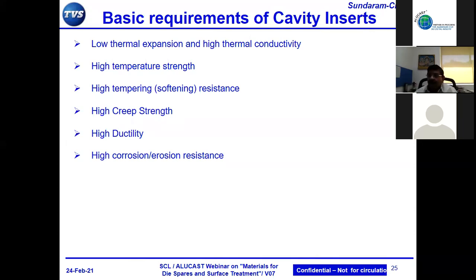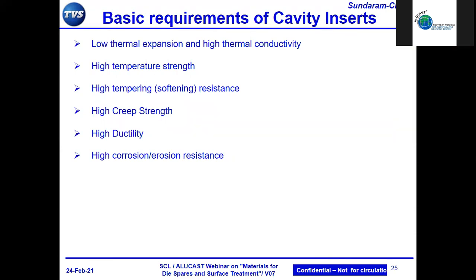Yeah. There are two aspects of this, Mr. Giri. One is, soldering could happen because of high temperature, as you rightly said. You have a high thick mass, you have a high temperature there, and soldering could happen. Soldering is basically a phenomenon where you have a chemical interaction between the tool steel and the liquid metal. So with a higher temperature there is more interaction between the tool steel and the liquid metal, and that is why we use a lot of anti-soldering agents, so that we form an interface between the liquid metal and the basic die.